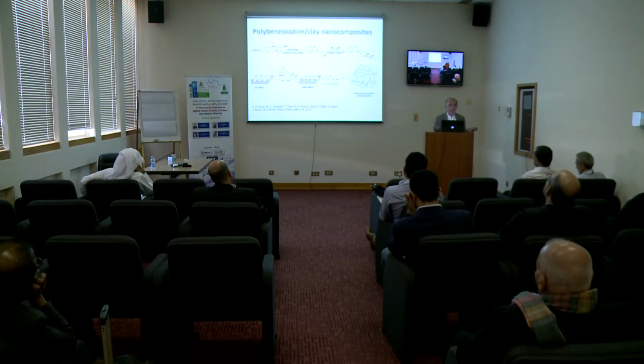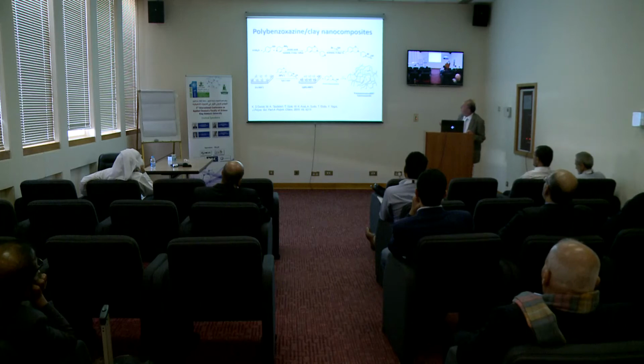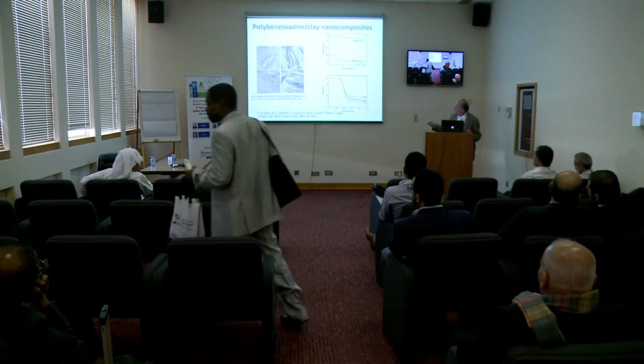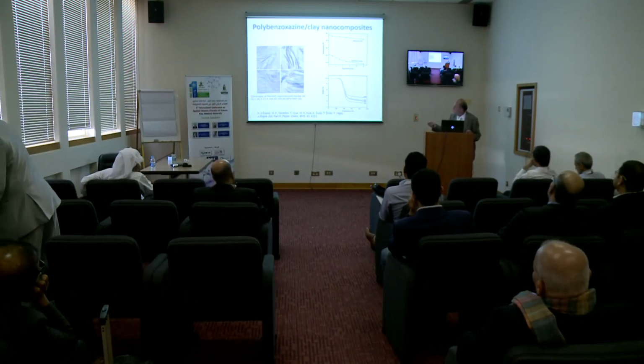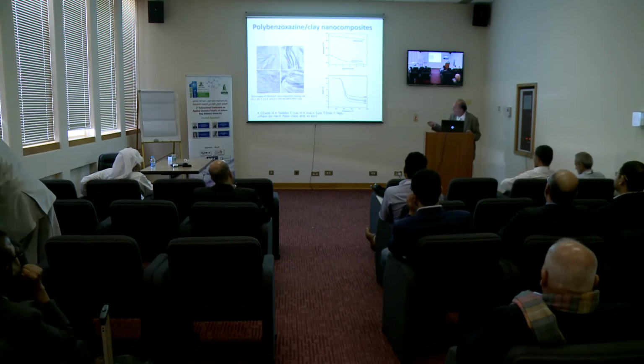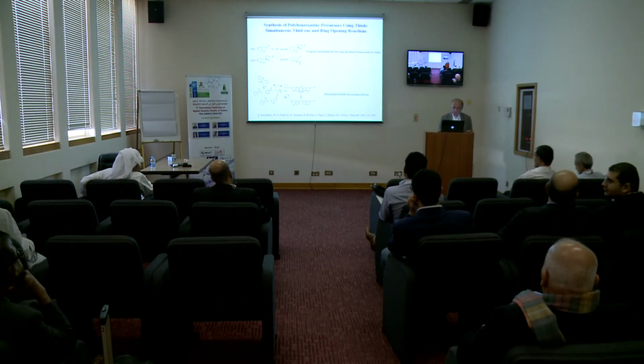Clay is a naturally abundant material. For example, in Tunisia, the clay is very nice and used in many industrial applications. We were able to quaternize it in collaboration with Japanese Professor Endo. This ammonium salt can be intercalated between the layers, and by adding additional benzoxazine, you have a highly thermally stable polybenzoxazine clay nanocomposite. And we were able to show intercalated and exfoliated structures. This is exfoliated, this is intercalated, present in the structure.